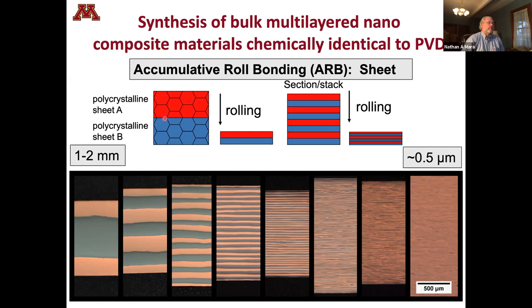The way this is done is you take two polycrystalline sheets of material, say A and B, which can be copper and niobium; we also did silver and copper, aluminum and iron, there's a whole bunch of different things you can do. Put them together and pass them through the rolling mill. The stack becomes shorter, and the overall sample becomes longer. You cut up that longer piece, stack it again, and pass it through again. By doing this over many, many repetitions, usually about 13 or so, you can start with maybe 1 millimeter thickness of copper and maybe about 2 millimeter thickness of niobium. It's basically a clad piece of niobium. And then you just keep stacking and repeating.